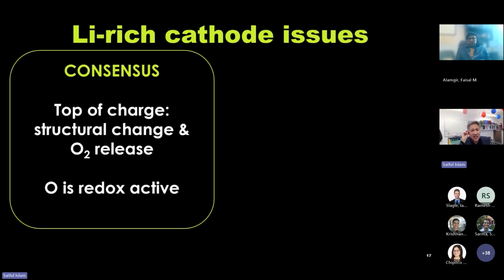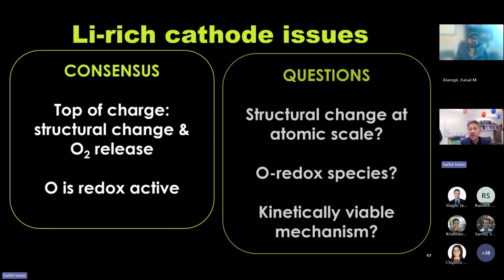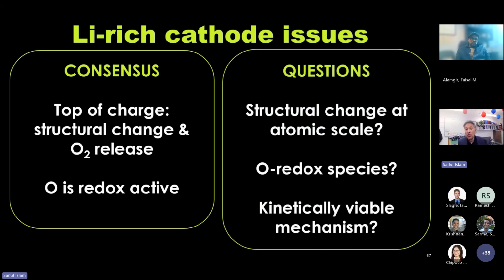So what is the consensus in these lithium-rich cathode issues? The consensus is that at the top of charge, there is structural change and oxygen release, or oxygen loss. There is anion redox, so oxygen is redox active. So what are the questions? What is the debate? The debate is, what is the structural change at the atomic scale, particularly at the top of charge? What is the oxygen redox species on charging? And what is the kinetically viable mechanism?